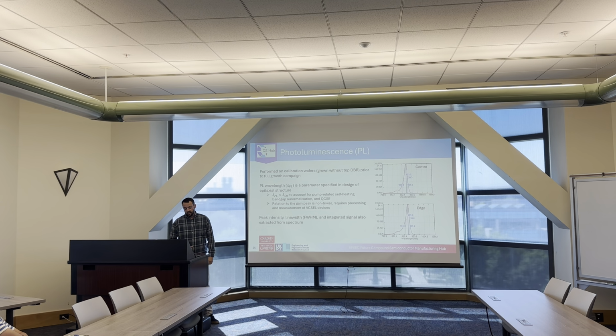Also extracted from the PL spectrum then the intensity, line width, and the integrated signal, which can indicate if you have a high density of defects in certain areas on the wafer.